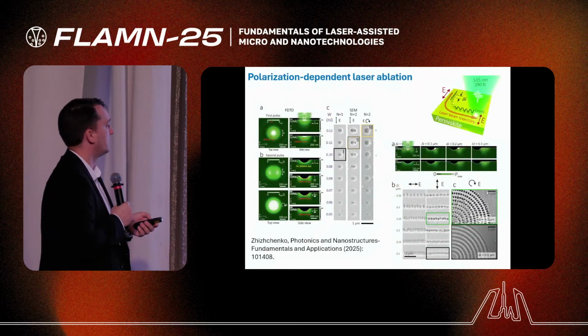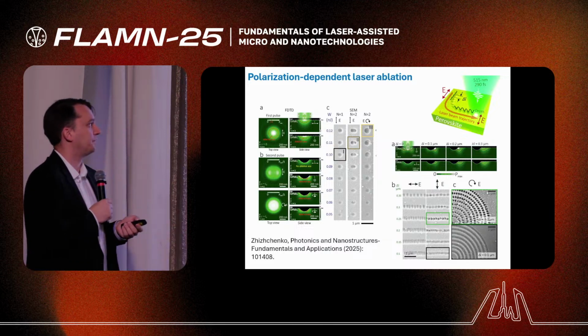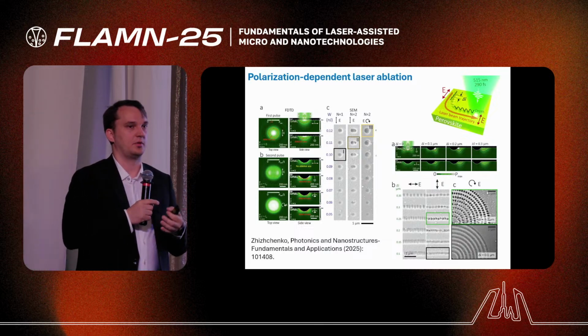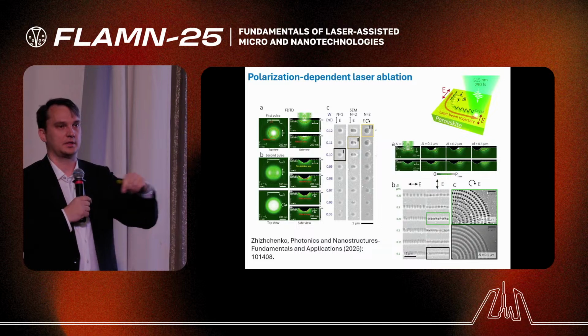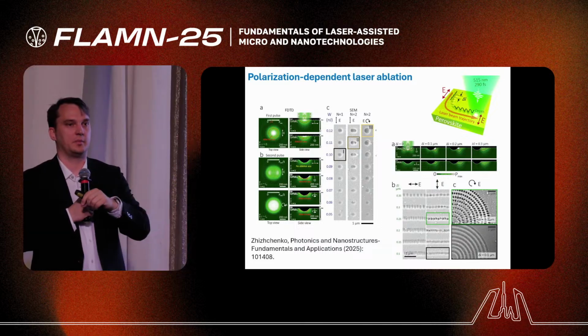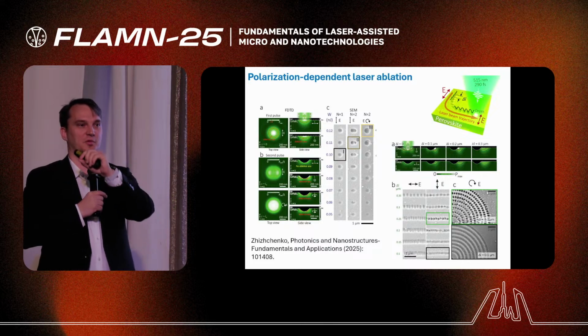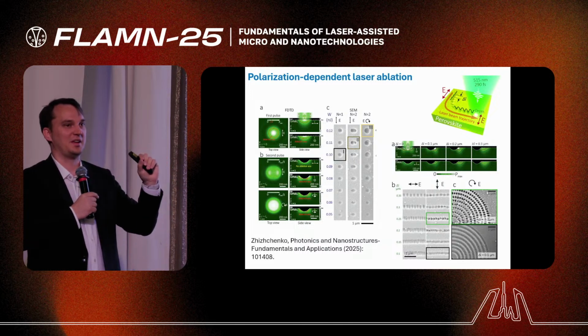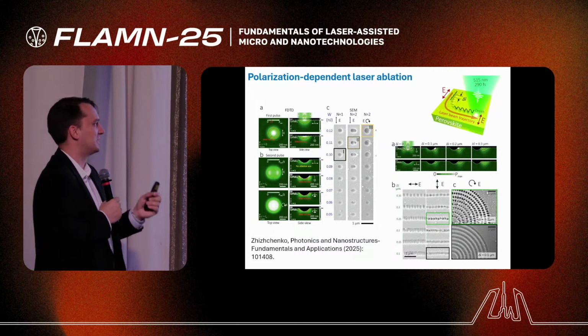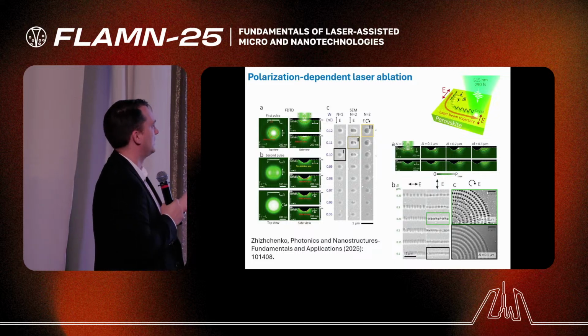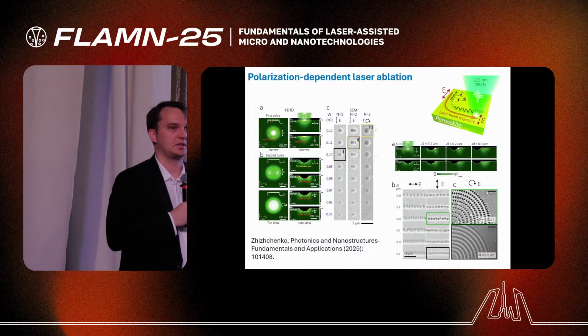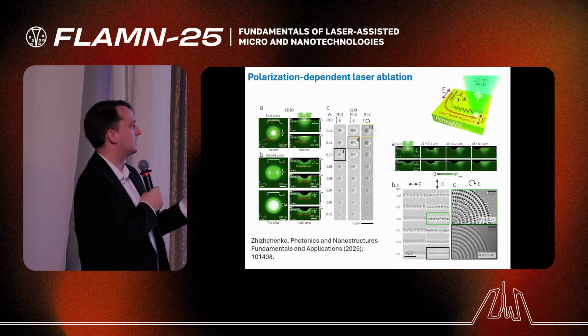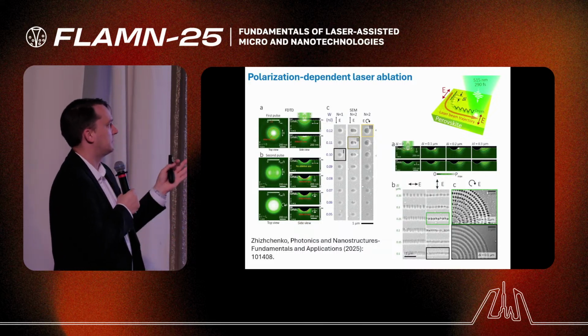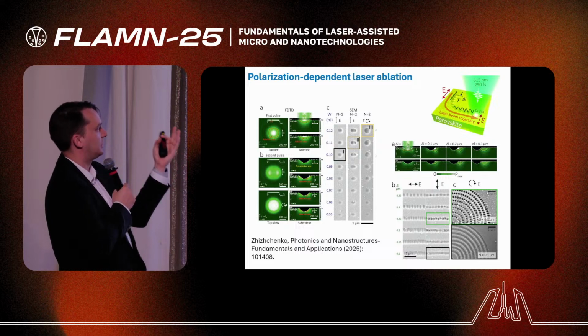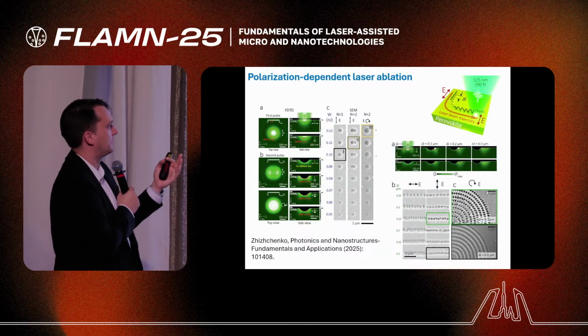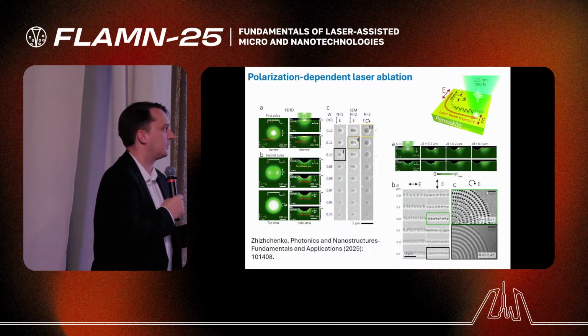And here recently we also studied how polarization affects the quality of ablation. If we would like to use a laser scan mode, it's very important to keep in mind which polarization you use. If you move in this direction, you have high quality, like a stripe. But if you move in the vertical direction, let's say, you can have worse quality. So here you see why. For smooth surfaces it doesn't matter, but once you create a crater and then shift your laser beam a bit, as in figure A, you see that for different polarization, if we shift our beam a bit to the right, we have different field distribution and the quality becomes a bit different.